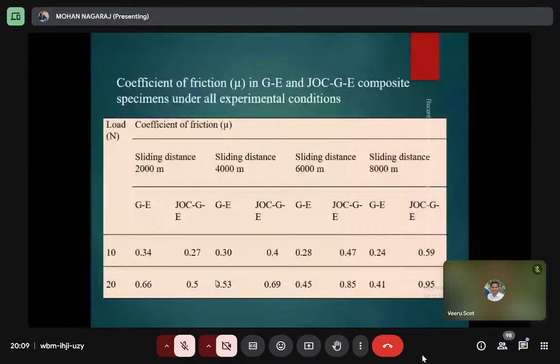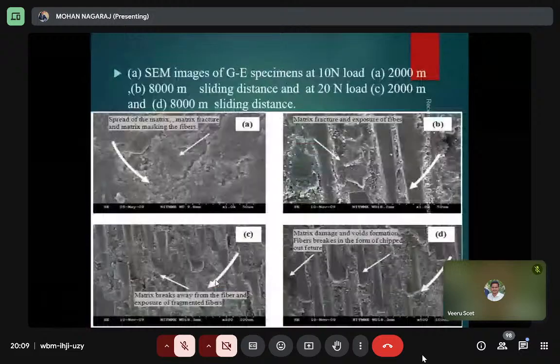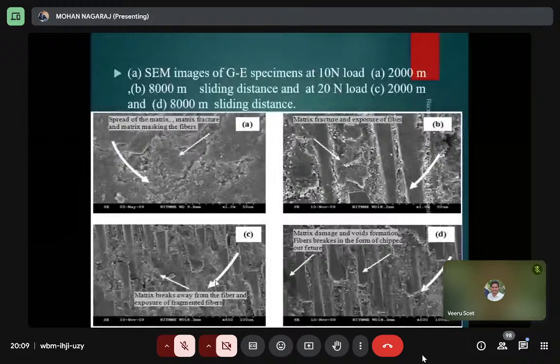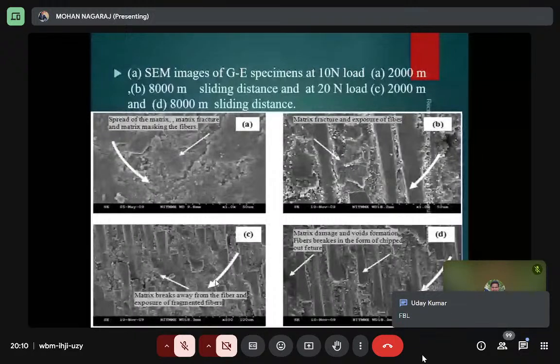These are the SEM images of the different composite materials at the lower distance and higher distance. Generally, at the higher distance, the materials will be more worn out. More damage is also observed as compared to the lower distance. And also, if you apply more load at more distance, more damage will be observed in the diagram.